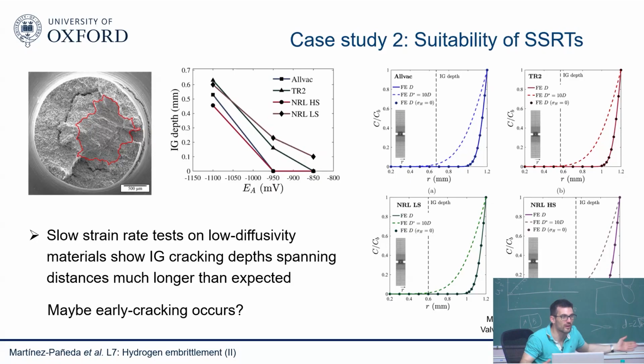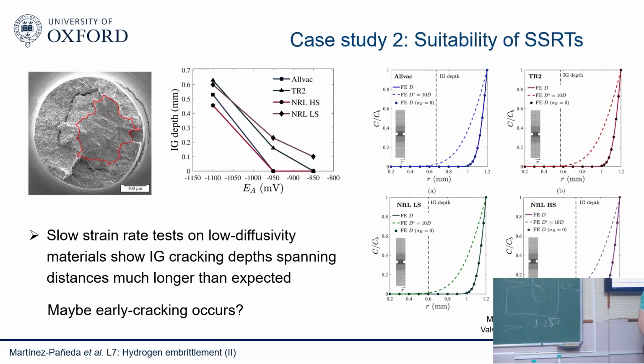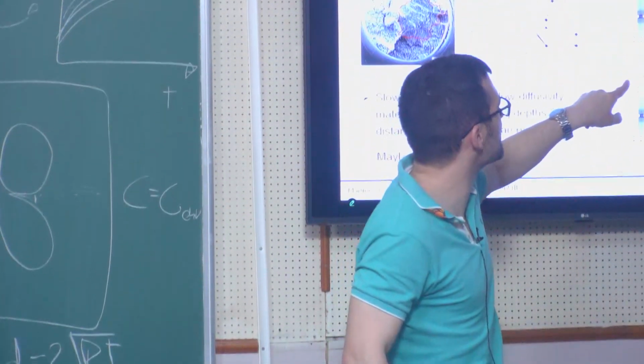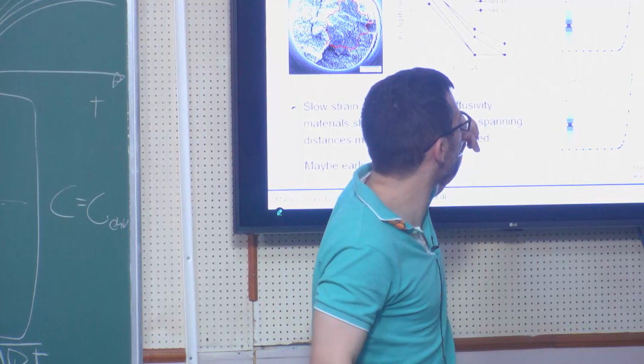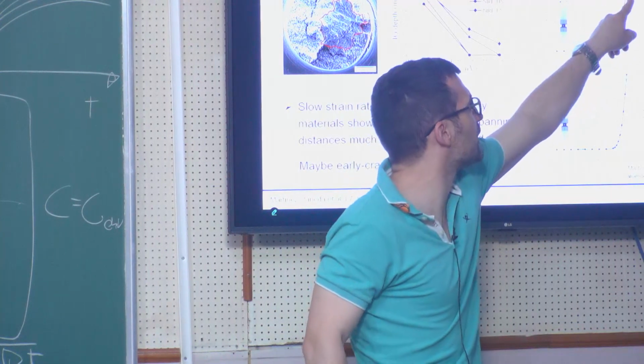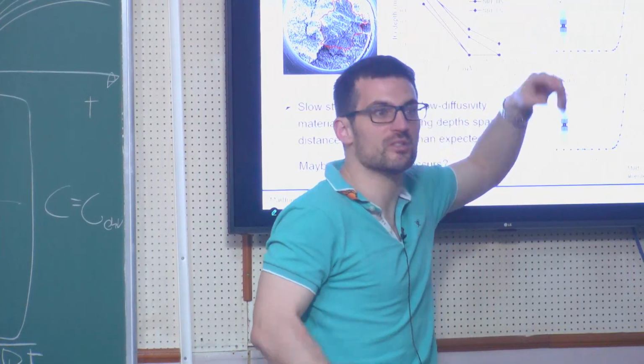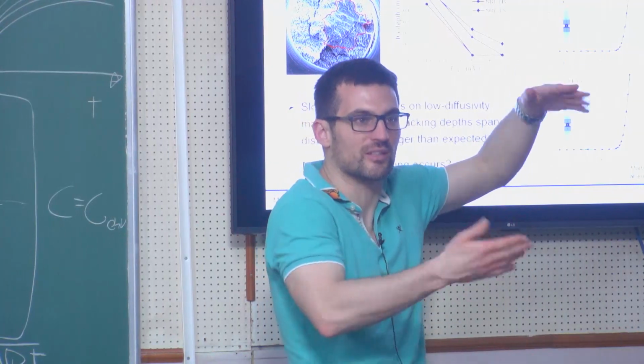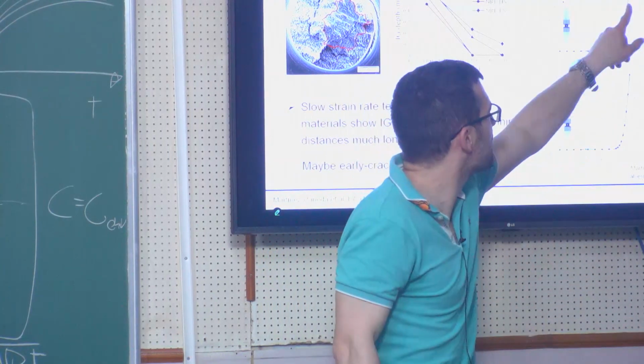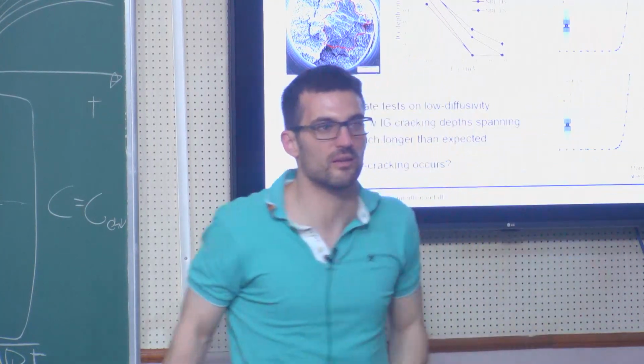So they were thinking, okay, the test seems fine from that perspective, but how can it be? So this is the outcome. This is what you see in the simulation after the end of the test. It's a slow strain rate test, so it still takes hours. It's not a quick test, but still you see very, very little uptake of hydrogen.